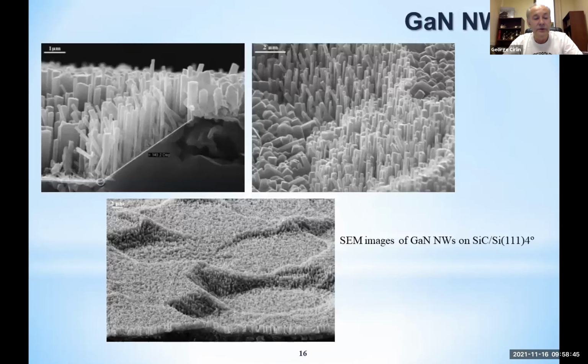What we also found is that sometimes we may get a planar substrate, but sometimes so-called vicinal substrates. In this particular case, on the surface, we may have different orientations of the facets. For example, we may have a 111 surface and something like a 113 surface, and this tilt angle corresponds to the vicinity of the substrate. And we also see that the morphology of the nanowires is different on the planar surface or on the vicinal surfaces.